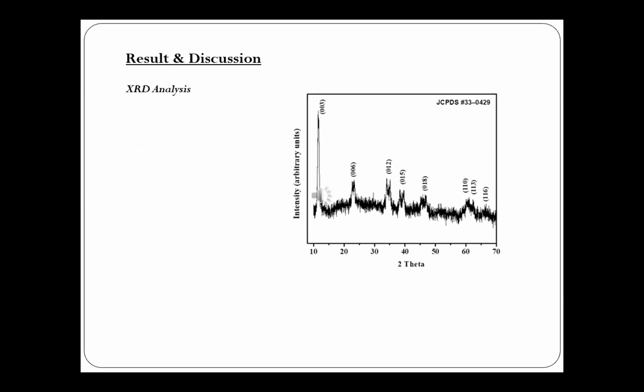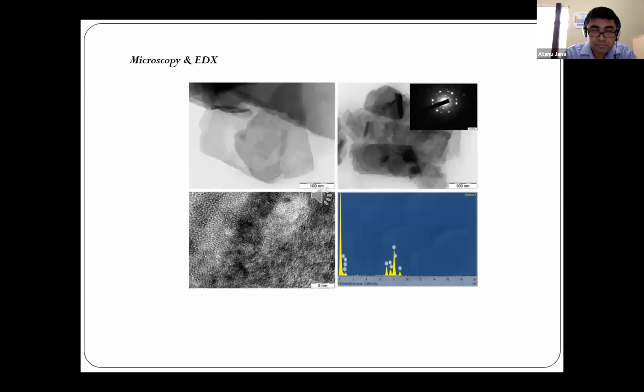Once we are done with the synthesis methodology, we have to characterize the obtained material using different experiments; I made use of XRD, TEM, EDX, and BET. XRD is used to study the phase structure of the prepared compound. Here we can see this material exhibits major characteristic diffraction peaks at 2 theta values of 11.1, 22.1, 34.4, and 38.6 degrees, representing the 003, 006, 012, and 015 planes of the hydrotalcite-like LDH, layered double hydroxide phase. Next, please.